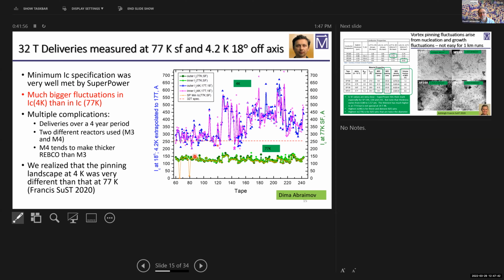We got about 10 kilometers of tape for our 32 Tesla magnet. And this represents the timeline going from left to right. They specify their tape based on a 77 Kelvin liquid nitrogen self-field. And actually, they did a very good job there. You see they're around between 125 and maybe 150 amps. But here at low temperatures where we were making our magnet, God, look at all these incredible fluctuations of properties. And this is because of the very complex interactions that occur between the quantized vortices and these insulating defects in the material, which enable the establishment of flux density gradients.